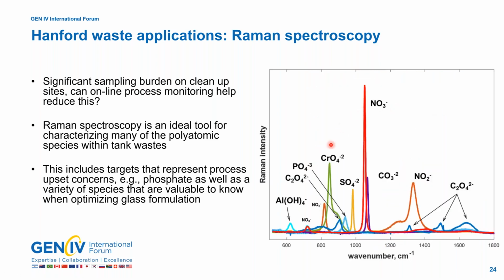In fact, this shows the Raman spectrum of those components that I just mentioned on the previous slide: nitrate, carbonate, nitrite, oxalate, chromate, sulfate, phosphate, aluminate. All of these species are Raman active, with very strong signals. And just to mention, the peak height or peak area under each curve is generally proportional to concentration. These are pretty much separated quite well. In fact, using the chemometric analysis multivariate technique that Amanda had talked about previously is how we measure these in very complicated mixtures.